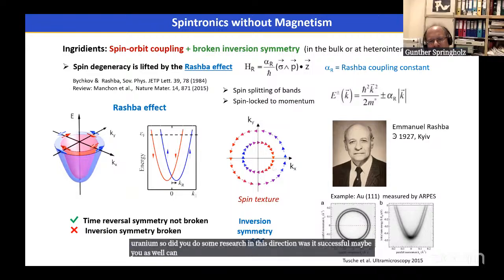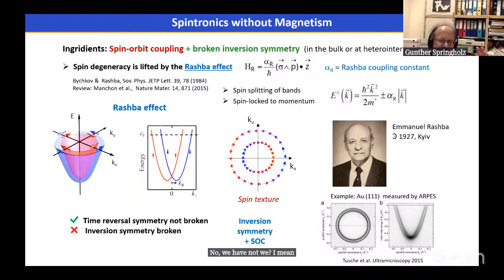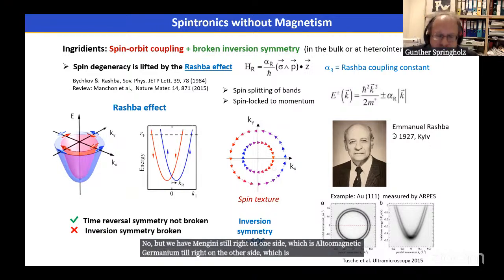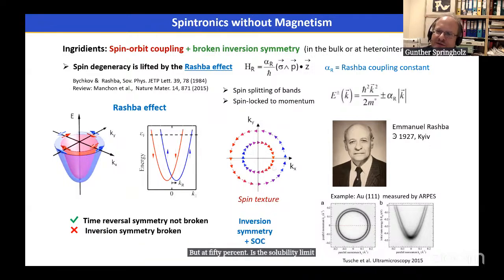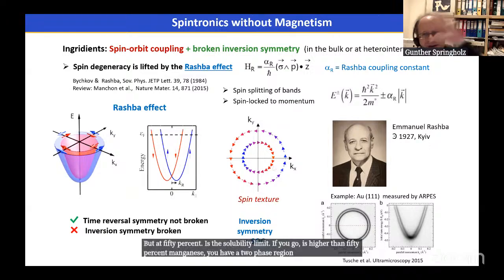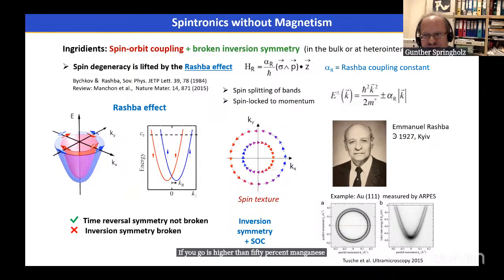We have not. I mean, if you look at the phase diagram for germanium manganese telluride, we have manganese telluride on one side, which is altermagnetic, and germanium telluride on the other side, which is ferroelectric. But at 50% is the solubility limit. If you go higher than 50% manganese, you have a two-phase region where you have manganese telluride plus some precipitates of germanium manganese telluride or other precipitates. So it's no longer a well-defined uniform system.